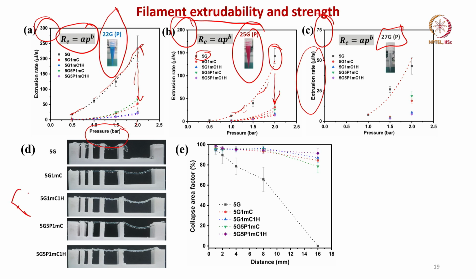This is the filament fusion test or filament collapse test, whichever way you call it, it is all the same. Now, when you go from 5% GelMA to this particular composition, 5% GelMA, 5% PEGDA, 1% modified carboxymethyl cellulose, 1% hydroxyapatite, filament strength is very good, it is very stable. Whereas there is sagging here without hydroxyapatite, and without PEGDA there is also sagging, and 5% GelMA does not pass through this filament collapse test at all.